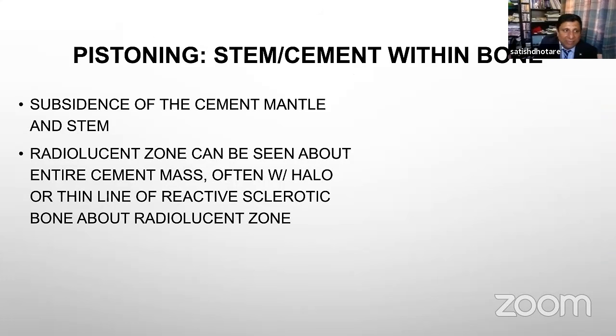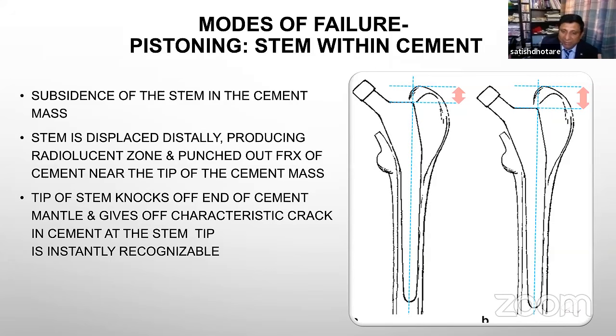The next is when both cement and the stem are within the bone, and that leads to a radiolucent line, which you'll see all around the prosthesis, and that will lead to the failure of the prosthesis, which will either be a fracture or a breakage, depending upon the stress and amount of fatigue it goes through.